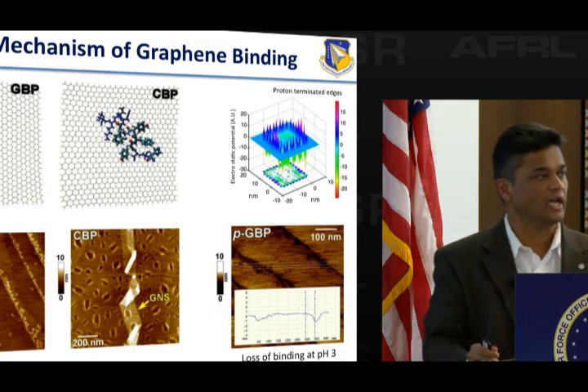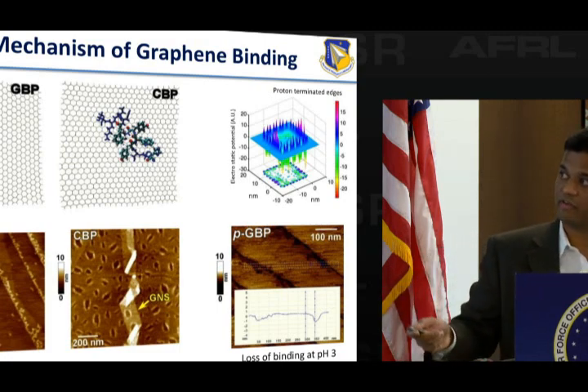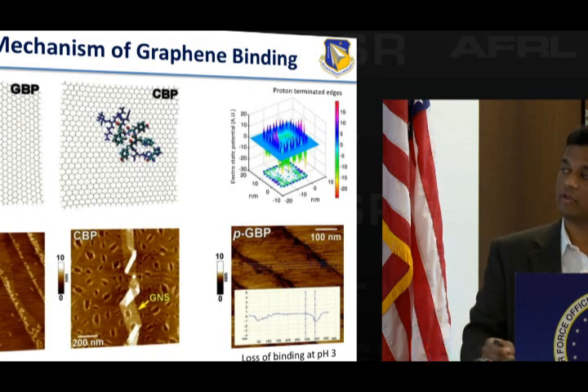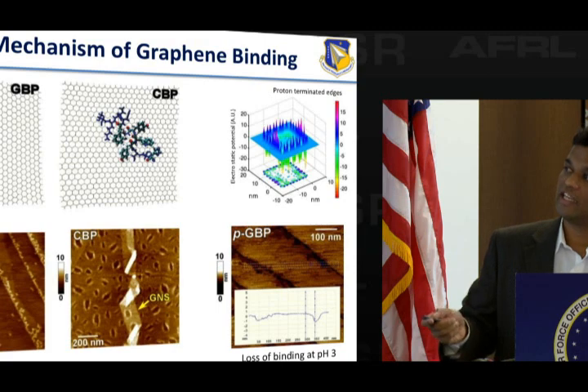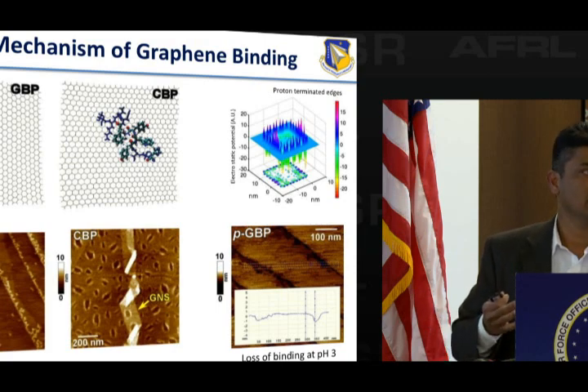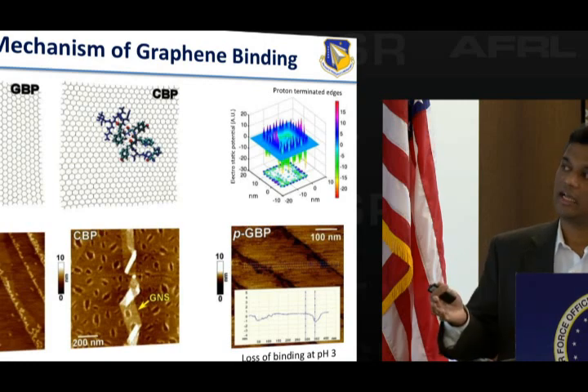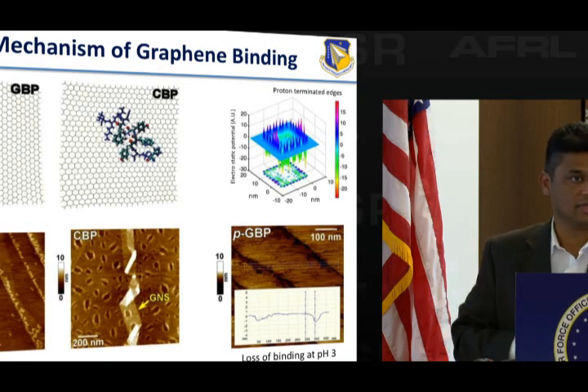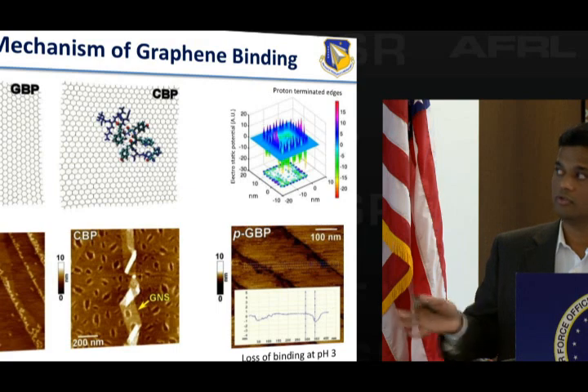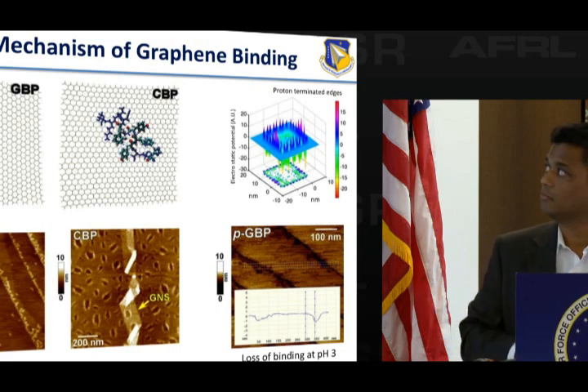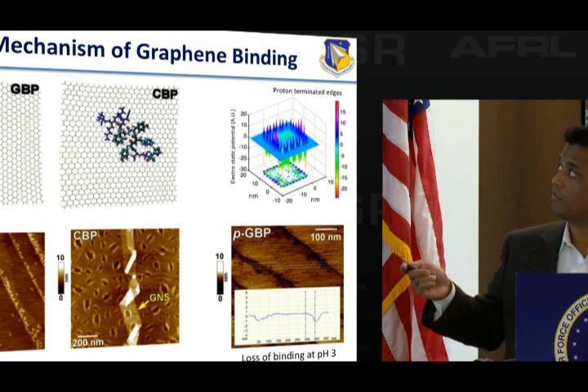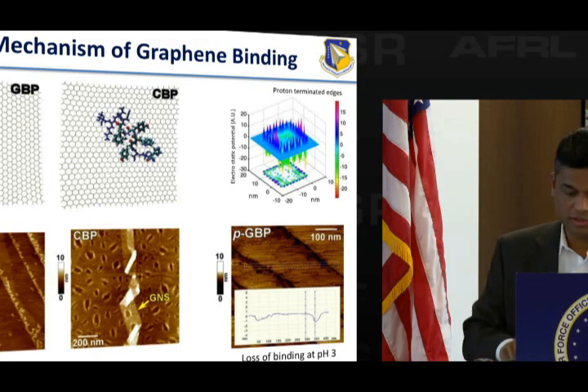So you can actually use pH as a way to control, because computational methods we developed in the lab have shown that a specific amino acid interacts with the edge. The edge is proton terminated, so you think that you would need some negatively charged groups to bind onto that edge. So if you knock off that group, you disrupt the binding activity. And this is just showing you that map of the proton-terminated edges on a graphene sheet.